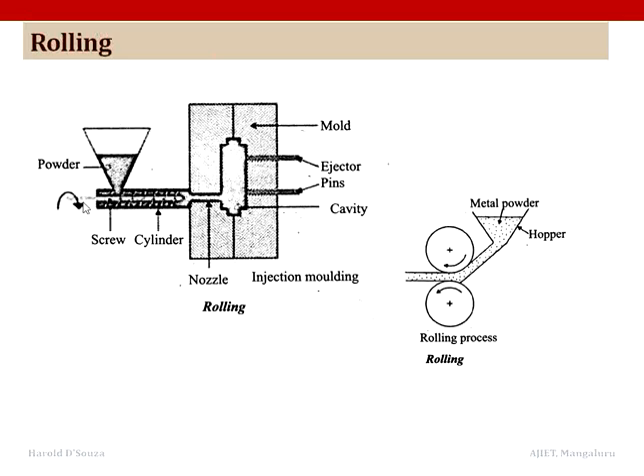Rolling. Now this method is used for making continuous strips and rods having a controlled porosity with uniform mechanical properties. In this method, the metal powder is fed between the two rolls which compress and interlock the powder particles to form a sheet of sufficient strength. It is then re-rolled and heat treated if necessary. The metals that can be rolled are copper, brass, bronze, nickel and stainless steel.